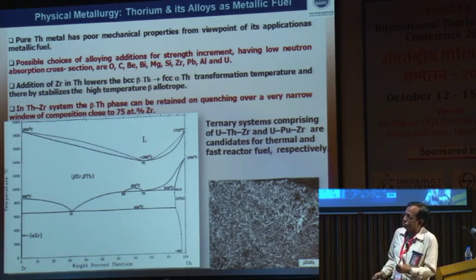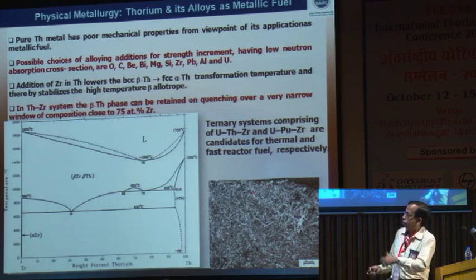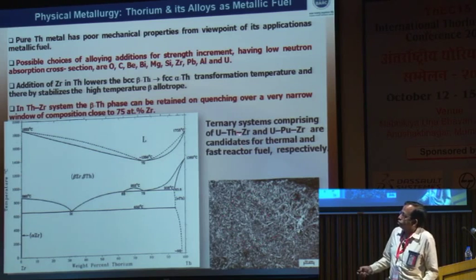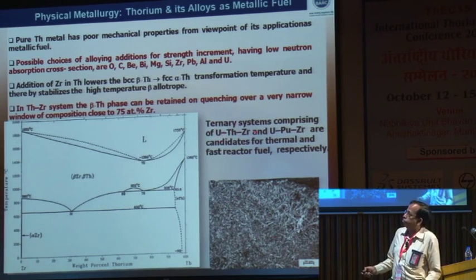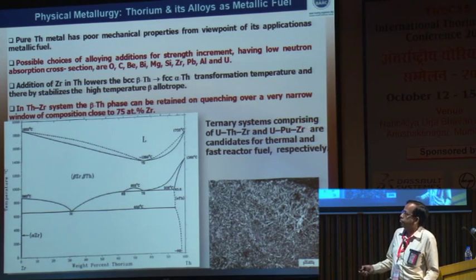So this is the zirconium-thorium system which we are studying here, and in this case, if you add zirconium, the beta phase field will be enlarged, and you may be able to retain the beta phase at room temperature in concentrations like a 75 atom percent zirconium alloy. It may be possible to retain it at room temperature also. So this is the initial macrostructure of the thorium-zirconium alloy that has been produced in BARC. We are also studying ternary alloys, that is uranium-thorium-zirconium or uranium-plutonium-zirconium, as fuel candidate materials.